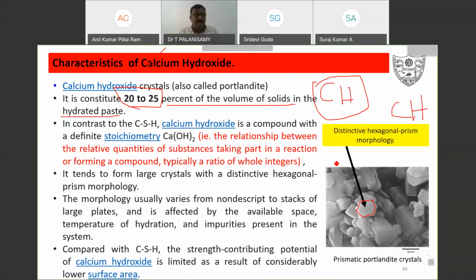What can we learn from this? CH tends to form large crystals with a distinct hexagonal prism morphology. The morphology usually varies from non-descript to stacks of large plates and is affected by available space, temperature of hydration, and the impurities present in the system. Impurity is nothing but unhydrated cement particles. Compared with CSH, the strength-contributing potential of calcium hydroxide is limited as a result of its considerably lower surface area. That is the problem. So CH does not contribute much to the strength of concrete, because its surface area is very low.